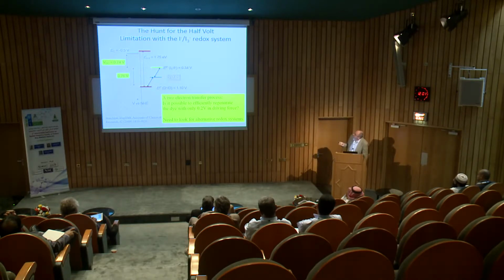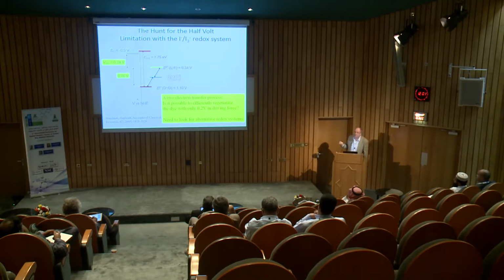The other option is to move the redox potential more positive, as we say, in this direction, and in that sense gain a higher voltage of the cell. This also turned out to be very difficult because what you do if you change the redox system is that for other system than iodide, you open up a recombination process from electrons in TiO2 out to the electrolyte. This is slow for triiodide, but normally very fast for any other system.